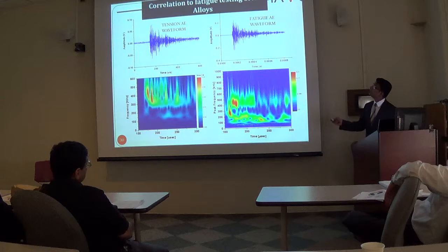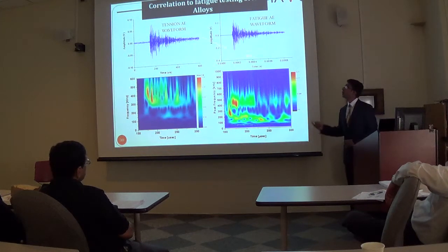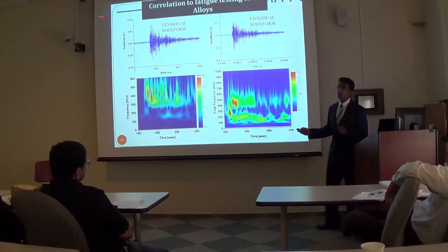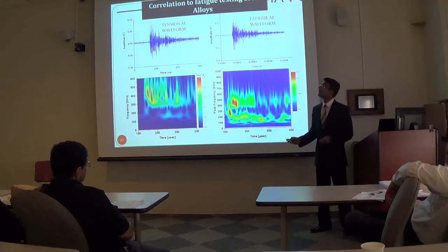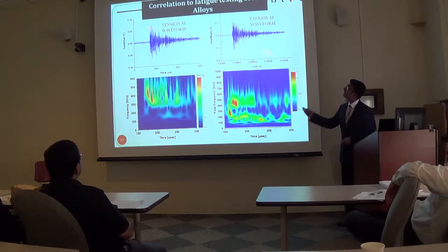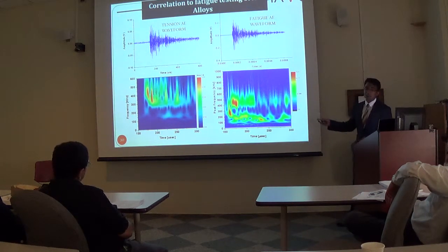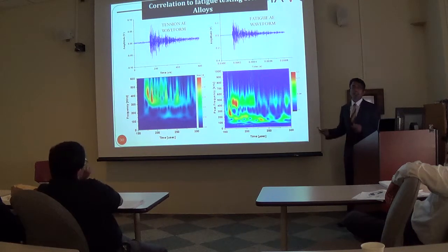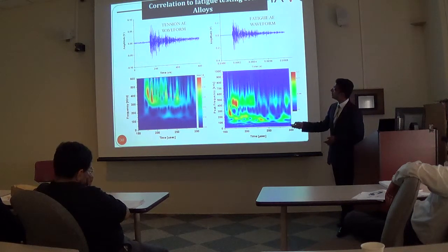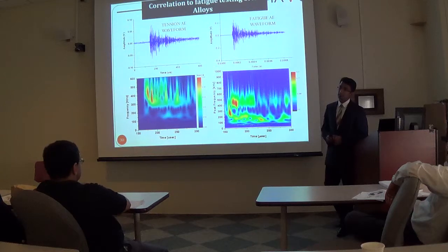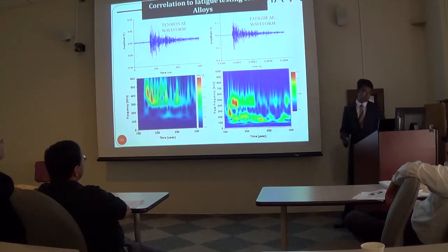The finally extracted AE waveforms were then compared to the tension AE waveform that was associated with the cracking that was used with the help of the DIC, and it can be seen that the waveforms that were extracted towards the end of the fatigue test had a very similar AE wave signature as shown here, and also the frequency analysis was seen to be very, very similar.